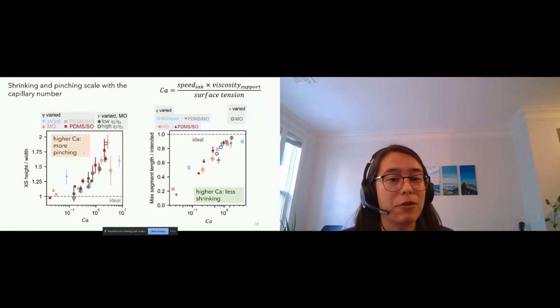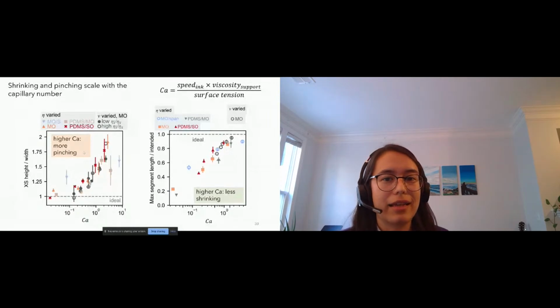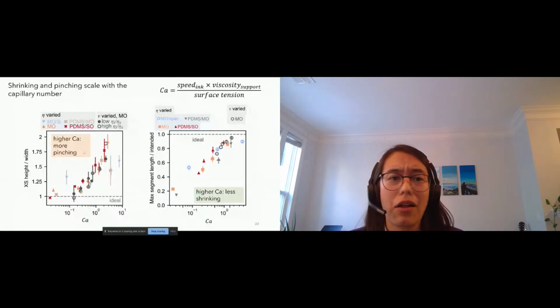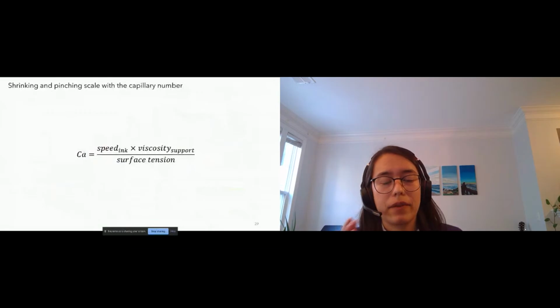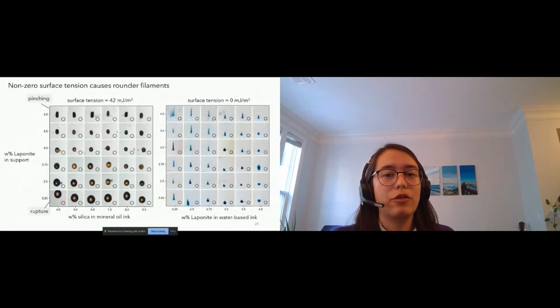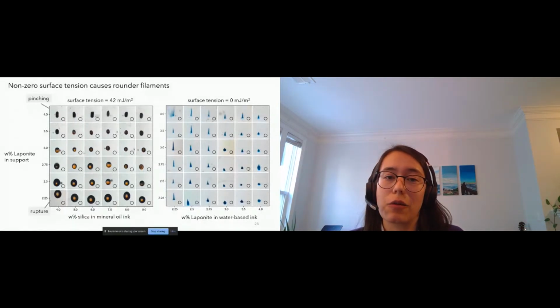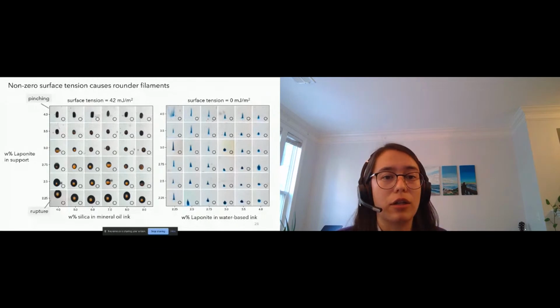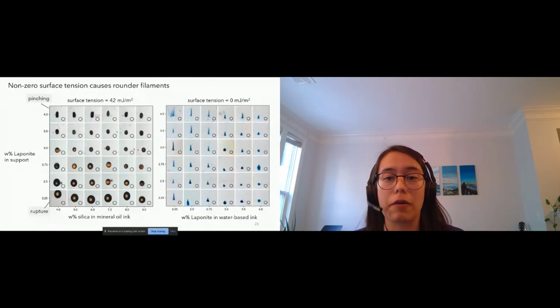However, these aspect ratios are not as tall and narrow as the water-based inks that we saw. And I'll also note that when you have these oil-based inks, you don't get any of the sharp edges or flat bottoms that you see in these water-based inks. So we always have rounder filaments, which is going to be an improvement for our surface roughness.